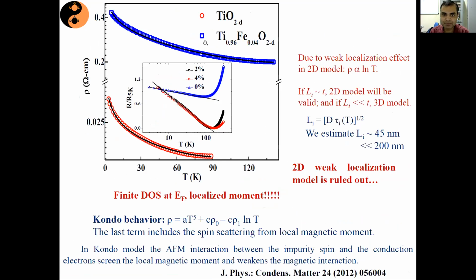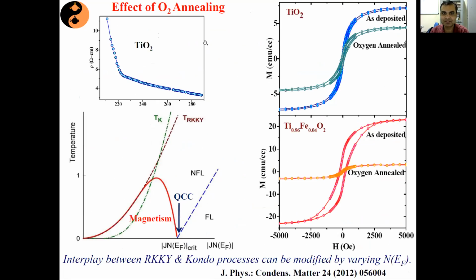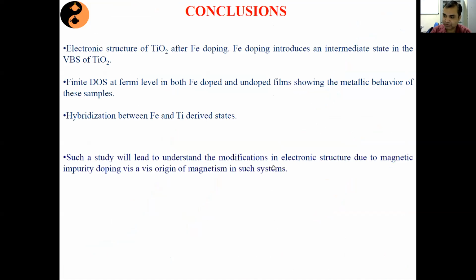Now, if you look at this particular behavior, you look at this resistivity. Now, this room temperature metal-like behavior is completely gone. Now, it is entirely semiconducting in nature. And if you look at their magnetization, the magnetization after oxygen annealing completely comes down, because we have got rid of oxygen vacancy, or in other words, the charge carriers available to us. So I will conclude my discussion for the day so that we will have some 10 minutes for discussion.